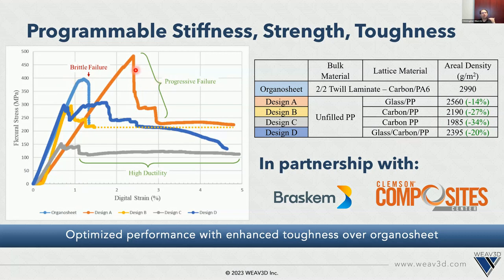What we noticed with all of these lattice reinforced parts is the way that we had set up this structure, where it was a sandwich of lattice, then pure polypropylene sheet, then lattice. What effectively happened was the top side of the panel would have a compressive buckling, and it would give you this kind of progressive damage zone that you see here, and then it would plateau. So you would actually be able to continue loading the part, it would continue absorbing energy, continue deforming. And we actually had to stop these tests because we reached the limit of the fixture. So we didn't actually fully break any of these panels.